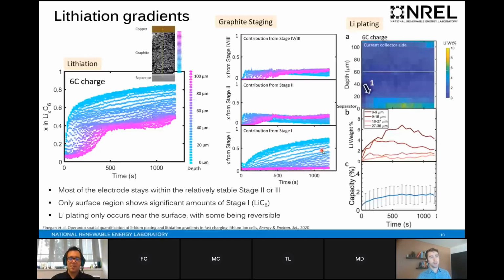And then we also see that when we reach the constant voltage stage and go to low current, some of that lithium plating is reversible. So we see a decrease in the lithium weight percent after a certain amount of time. Some of the lithium plating is irreversible, and we talk about that in the paper as well. At some point, the magnitude of lithium plating becomes irreversible, and you end up with major capacity loss that can never be retrieved in that cell again.